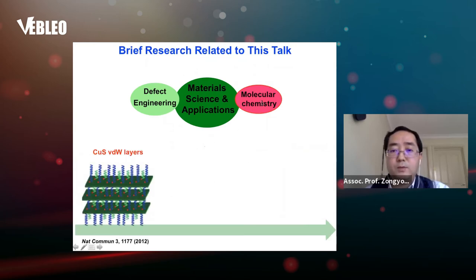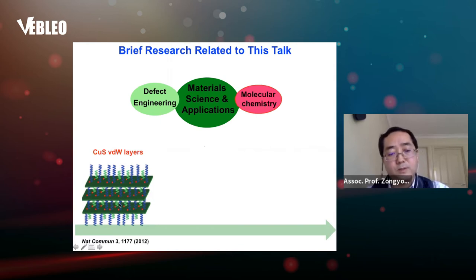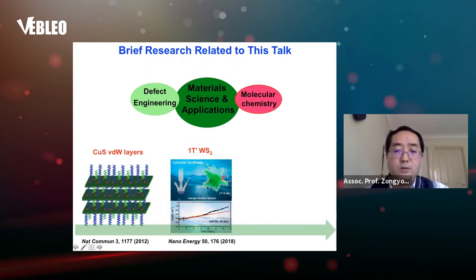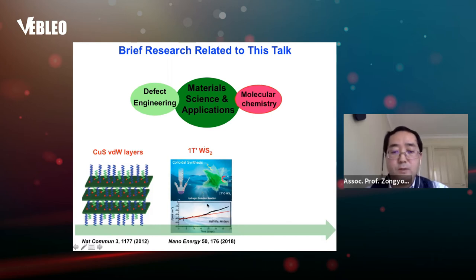We also study molecular chemistry. About eight years ago we used a template to synthesize 2D materials — single-layer based 2D materials — which are very good for liquid exfoliation. Applied to battery study, they showed quite stable and good performance. Two years ago we also developed a new structure: the 1T' phase of tungsten disulfide (WS2). We found that this structure has a huge effect on reactivity and stability for the hydrogen evolution reaction, bringing a positive effect.